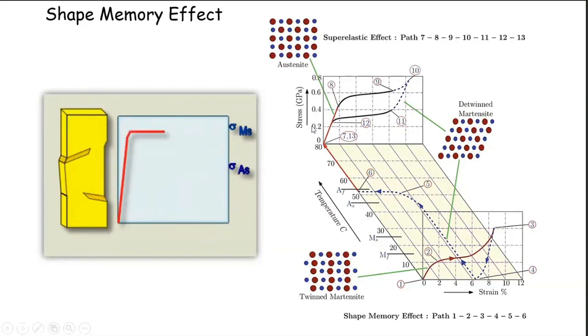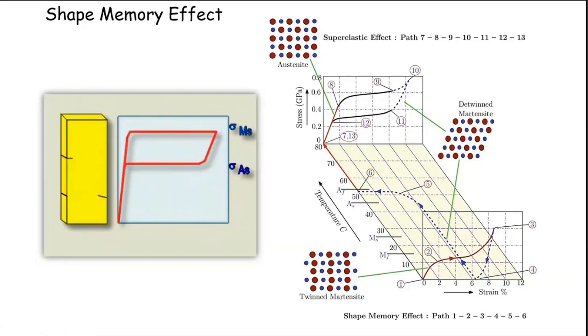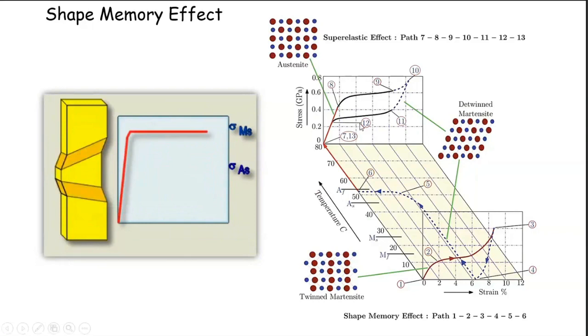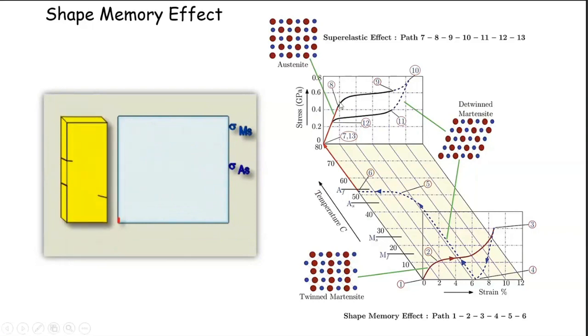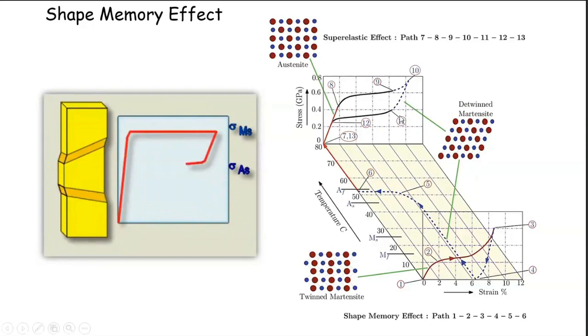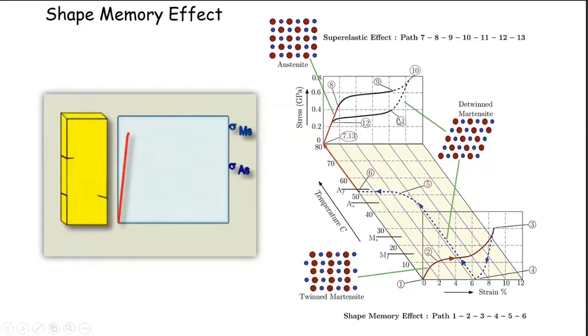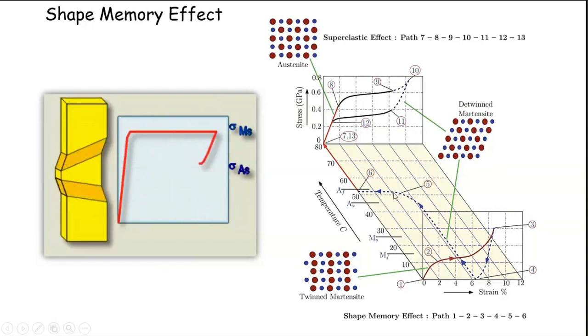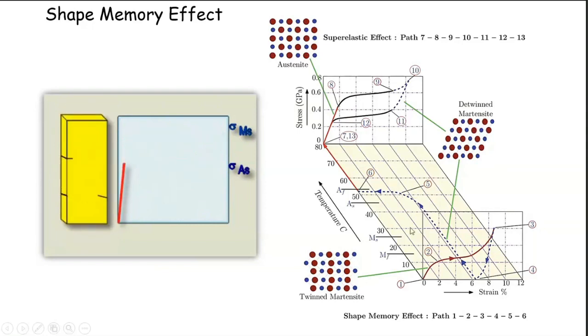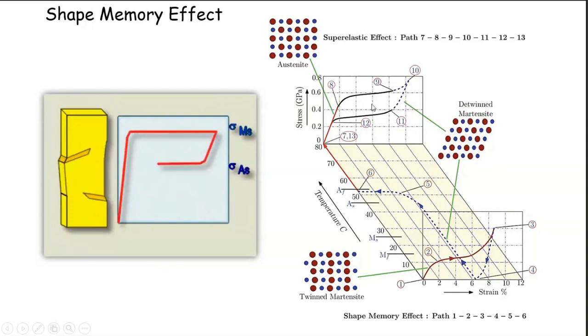And much like you had seen this AS and AF, or the MS and AS, the temperatures at which you get martensite and austenite, you'll have an analogous stress here: the initial stress at which martensite will form is sigma MS, and the stress at which it will start returning is sigma AS. So you can see this behavior is analogous to what happens when you're cooling. So you're having a transformation isothermal under a force, in the sense that you're giving a supercooling when you're cooling it. So you have a supercooling and superheating, much the same way you have a superheating and supercooling in an analogous fashion when you stress it and unload it.